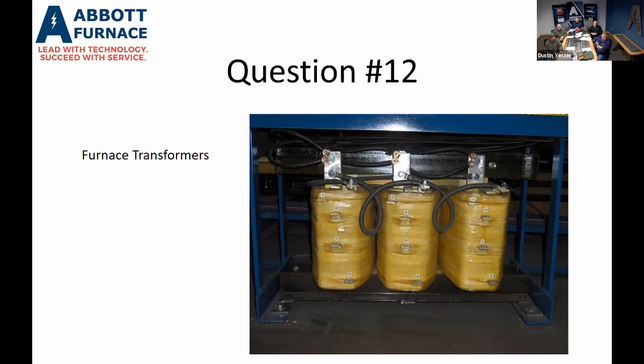So you have to determine, if you look at your SCRs, the SCRs also have what they call a current limit on it. And that's going to limit the current that's going out to this transformer to protect it from overheating, if you happen to take too high of a tap and reach that max current. The max current is determined by your transformer size. So the example is, if you have a 60 kVA transformer, you take 60,000 divided by the voltage that you're supplying to that transformer, which is typically 480 in North America. Then you divide that by the square root of 3, which is 1.732. And that'll tell you what your amps are.